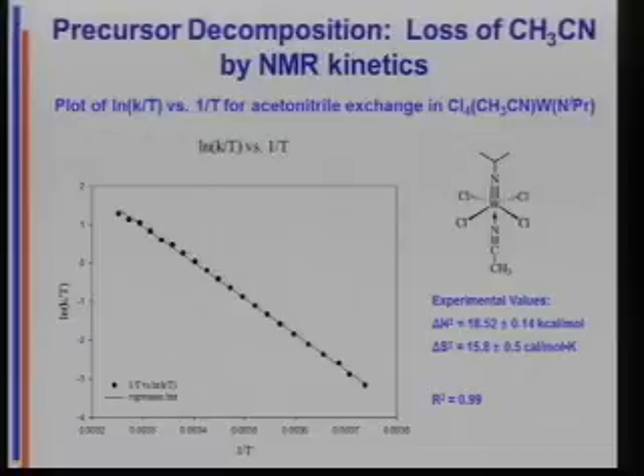And if you're good at converting 1/T to T in your head, this reaction is fairly fast between 50 and 80 C, just a little above room temperature. So I'm good for losing my trans acetonitrile.